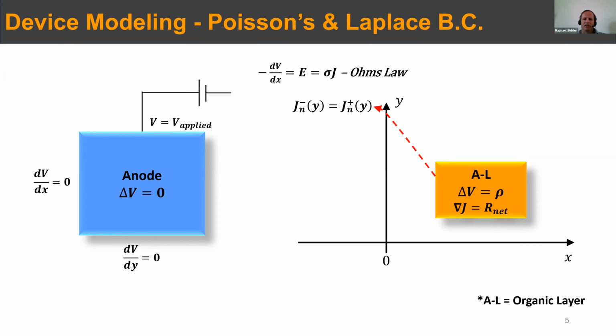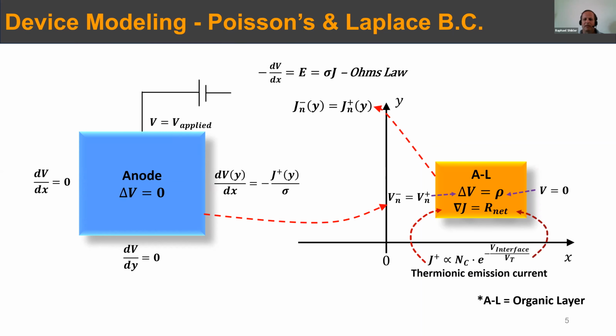To translate that into a boundary condition on the Laplace equation, we just use Ohm's law, and therefore we can translate the current into a boundary condition on the electric field. Then we have a well-defined Laplace equation, which can be solved. From that, we can calculate the distribution of the potential and electric field within the anode, and use that as a boundary condition for the active layer itself. And you go back and forth until you get something which converges.